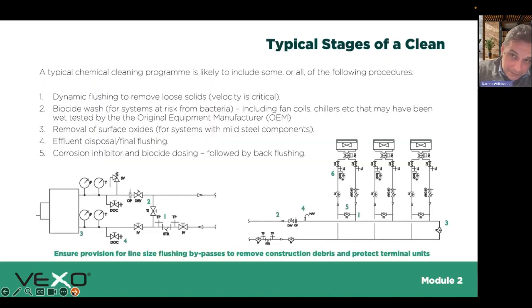And then we have the different stages of the clean to consider. When the system's first filled, generally it's recommended it's filled with treated water, rather than raw water. And you don't want to fill a system and then drain it once you've filled it. It actually makes things a lot worse. But typically the approach the water treatment company will take is dynamic flushing. This is where they would take terminal units and put them into a bypass situation before you even run the pumps. Once you've got those pumps running and everything's in bypass, they would then look to dynamically flush, which means they look at the velocity.